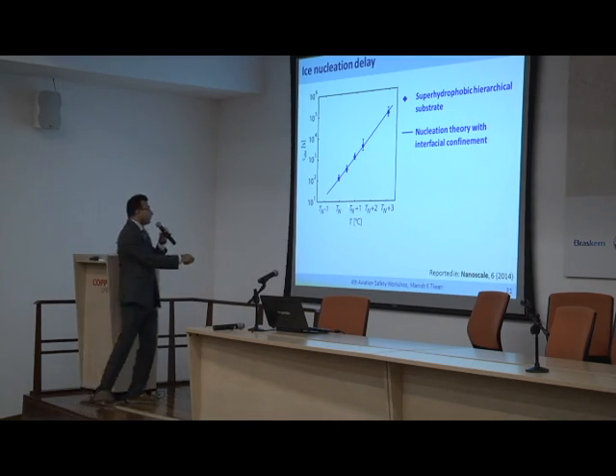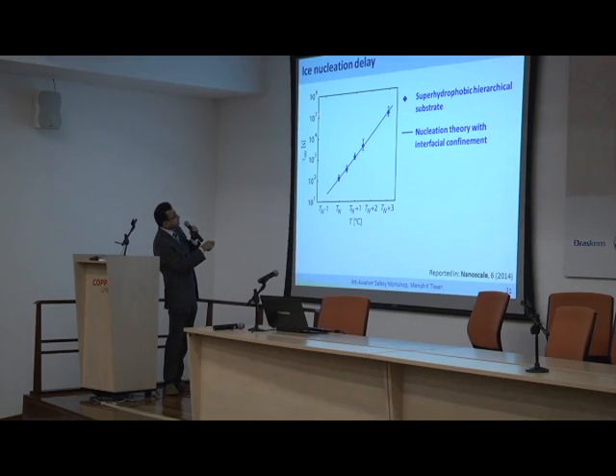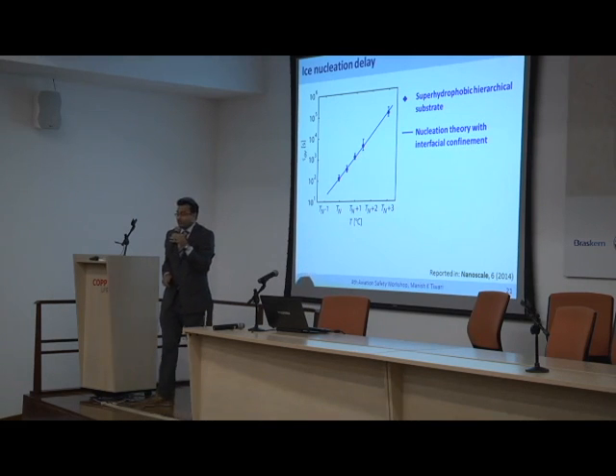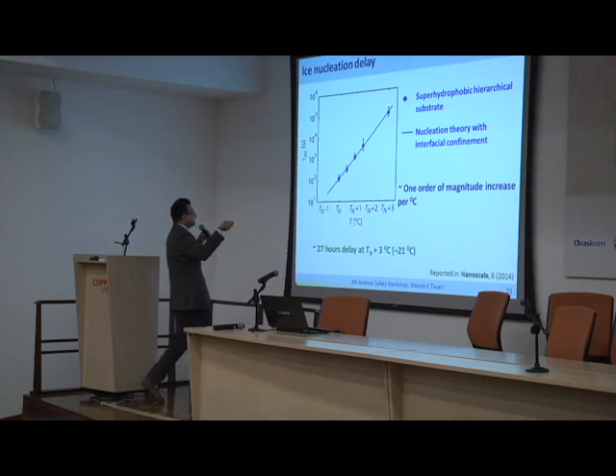Now I go by 1 degree higher. I go 1 degree higher, I start to get to about 10 to the power of 3 seconds. And if I go about a few degrees higher, I start to run into 10 to the 5 seconds, which is about a day, okay? And I must tell you that this line is the fit part, and these are actual experimental data. True.